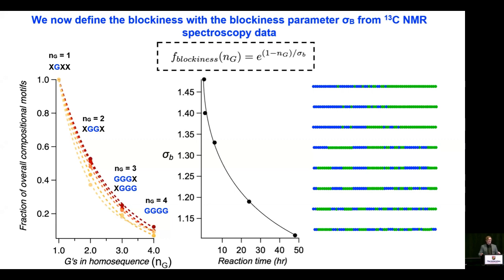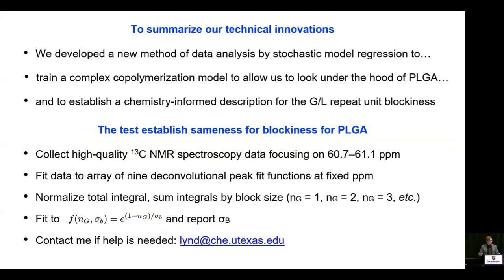And you can see that the blockiness parameter there decays exponentially as a function of reaction time. And so what you see is that initially the polymer is most blocky because of the establishment of that gradient early, and then transesterifications randomize that copolymer sequence as a function of time. And that is how we do it.